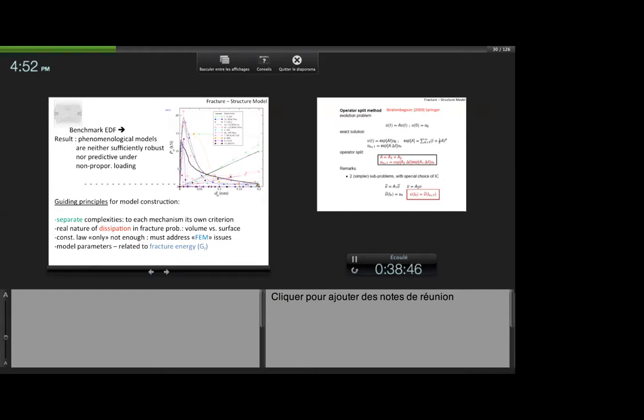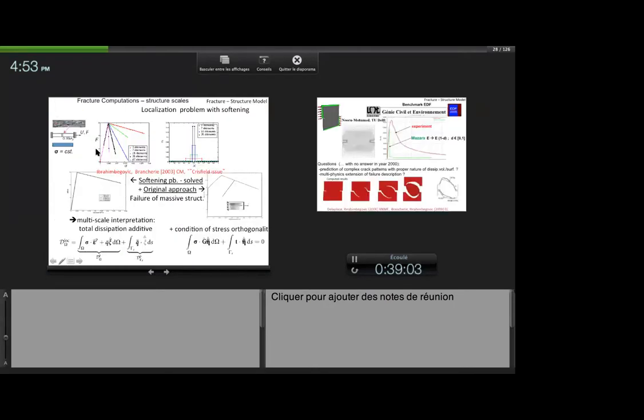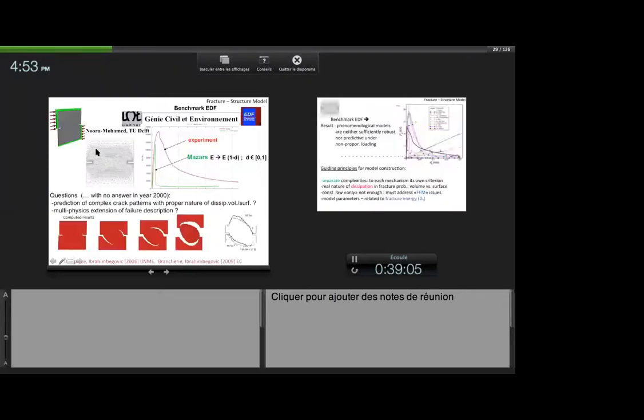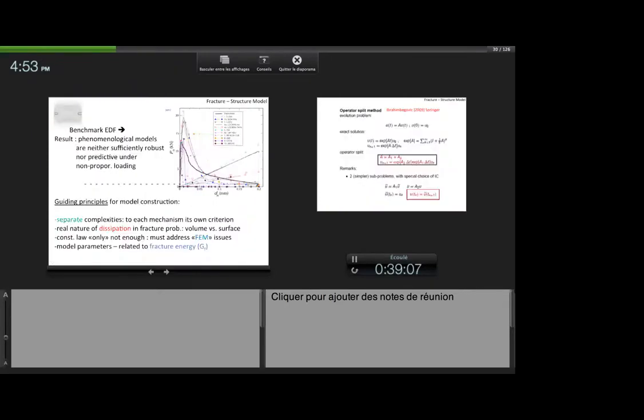So what went wrong? Well, people are using the finite element. In the finite element, every element has a homogeneous strain field. Let's say you have a constant strain triangle. So whatever you do, once you start failing, this element can only go berserk. And this will be the same thing as this bar that I was showing you. The more elements you put, the smaller dissipation you're going to have. And basically, you cannot repair it unless you change paradigm, change the way of thinking completely.